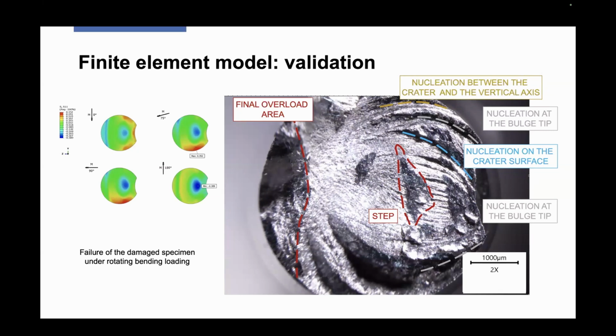And first of all, you can see that the critical area, comparing with the results of the fracture surface of the tested specimen, is that we have crack appearance in the areas where the maximum axial stresses occur during a loading cycle. We simulated only one cycle using a static calculation.